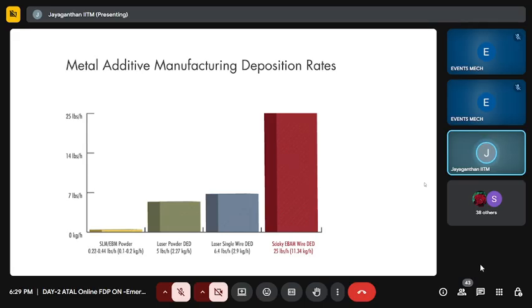Through fabrication processes like welding, we will do a lot of operations. We'll do welding operation to fabricate. You want to repair the weld or you want to join broken parts, you want to connect them, as long as it happens to be a non-critical part. You know about the role of welding actually. For weld repair, which one will you use? In fact, they propose wire arc based additive is helpful for weld repair. Let us say heat exchanger, the typical size and shape is micron or submicron. We always go for selective laser melting where the deposition rate is very, very less. I cannot use selective laser melting or electron beam melting for weld repair. The deposition rate is very less.